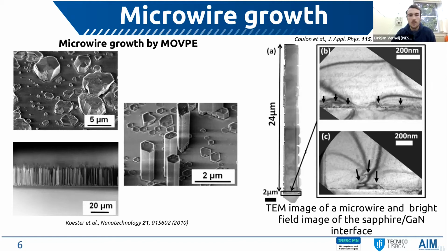Yes, so first of all, I have never done this process myself. Like I said, this is done in Grenoble, in France. But the way this works is that first they start with depositing a silicon nitride sort of mask on the sapphire substrate. The silicon nitride mask basically is not complete, so there are voids in the mask. And then they do nucleation of these kinds of islands or seeds, which are of gallium nitride. So these seeds are formed at the voids of the silicon nitride.